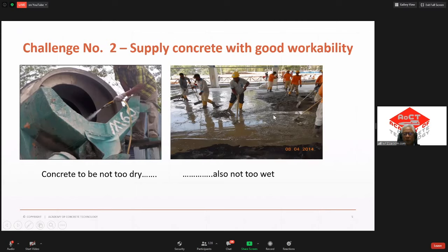Normally, cold joints are caused by disruption or delay of concrete supply, isn't it? Let's say you place this concrete, right? After 2 or 3 hours there's no supply, and then the fresh one comes in, and you know that the fresh and the old hardened concrete would not intermix. As a result, after many months, as the concrete starts to shrink, you tend to have a crack line appearing there. So these are the reasons why you need very good workability of the concrete, so that the workers don't add in water.